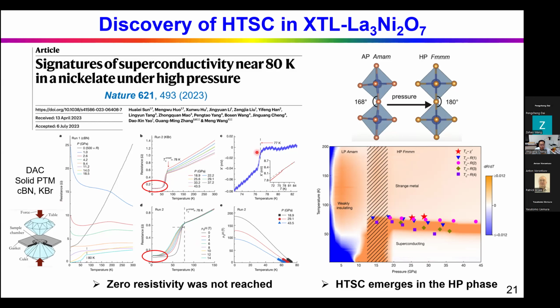In addition, they also observed some anomaly in the magnetic susceptibility. This is the original data. So after subtracting the background, they can clearly observe this drop. So this indicated that there are some signatures of superconductivity, especially the TC onset. The onset of the transition temperature is around 80 Kelvin. So even though zero resistivity was not achieved in this report, it's pretty exciting that there's high TC superconductivity in the bilayer nickelate under high pressures.